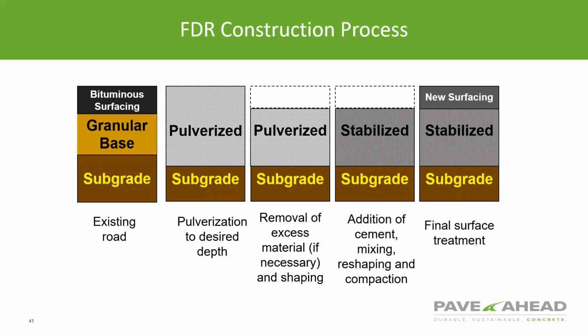And the cement content was almost reduced in half, purely from the fact that we brought some of those fines from the aggregate up into that blend. The asphalt alone was basically exactly 7 inches out there, so when we pre-pulverized it, there wasn't enough fines in there. So it took so much extra cement to create the fines that it needed, and it was so expensive to do. Just by doing a pre-pulverization at a different depth than what the actual process was going to be, we had fantastic results. And that was all on an FHWA project.